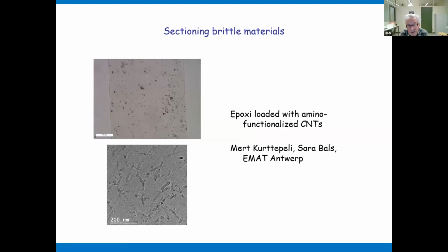Happens in biological samples these days: epoxy researchers load sample blocks with carbon nanotubes. Carbon nanotubes are harder than diamond. They are really hard. Now you can say it's not brittle, it's hard. And there was not a big problem, not much damage, as long as the carbon nanotubes were well dispersed. If the carbon nanotubes were agglomerated, I got fairly big damage.